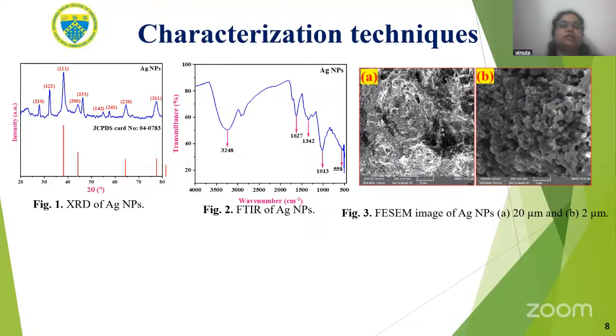Next, the synthesized silver nanoparticles were characterized with the help of various analytical techniques: XRD, FTIR, FESEM, and UV-visible spectroscopy. XRD peaks correspond to the 210, 122, 111, 200, 231, etc. planes. This confirms the planes of silver, indicated by the face-centered cubic structure of the nanoparticle. XRD measurement shows that the extract results in the formation of solid silver nanoparticles.